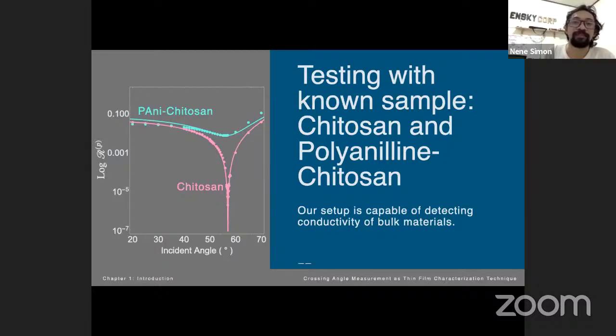Since PANI is a conducting material, we expect PANI chitosan to demonstrate a pseudo-Brewster angle, which is a behavior seen for conducting materials. Here, the cyan curve and the cyan dots are the theoretical and measured P reflectivity, respectively. And this shallow dip here gives us the position of the pseudo-Brewster angle.